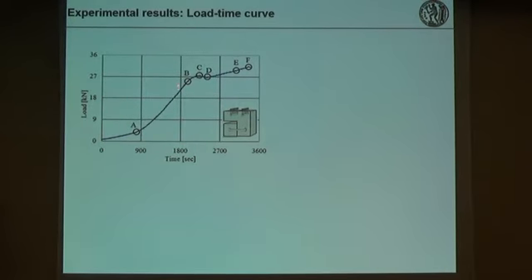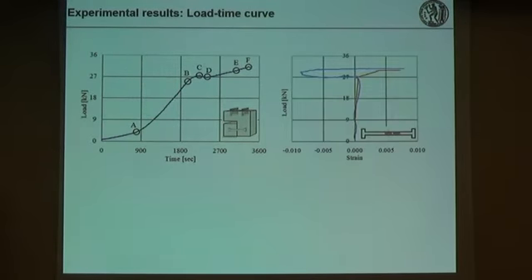After point B, the curve ceases to be linear, and it reaches a local maximum at point C, which is at 27.5 kilonewtons. This deviation from linearity can be explained by the yielding of the connector. And if we look at the results of the strain gauges, which, if you remember, were attached on the connector,